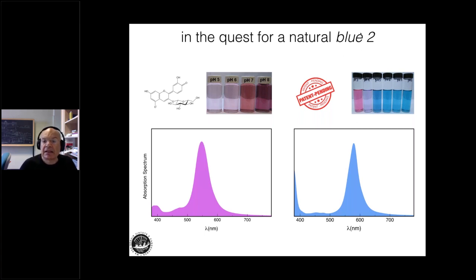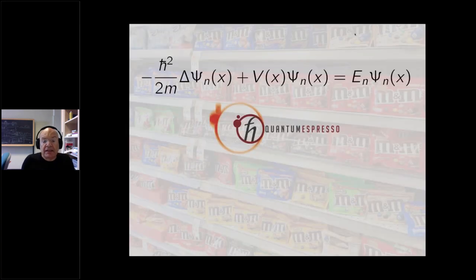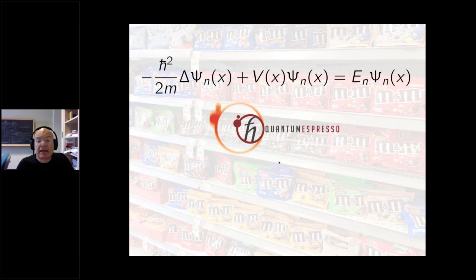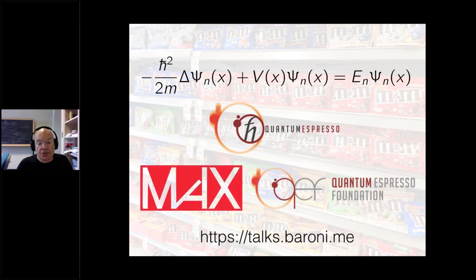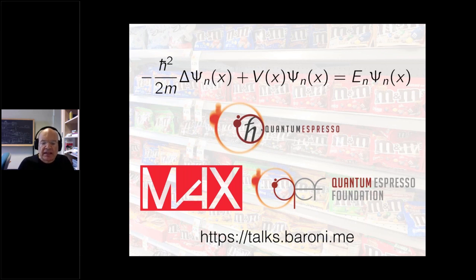By molecular simulations we identified the right substituent to turn the purple of cyanidin into blue. The chemical identity cannot be disclosed as a patent is pending, but the results demonstrate two important goals: the modified molecule is more stable than pristine cyanidin — stable not only at alkaline pH but also in moderately acidic conditions — and it has the right shade of color bearing the industrial name 'Bluetiful.' In the next two to three years, when you buy M&M candies on the supermarket shelf, you will find quantum mechanics inside — produced by Quantum ESPRESSO with the support of MAX.